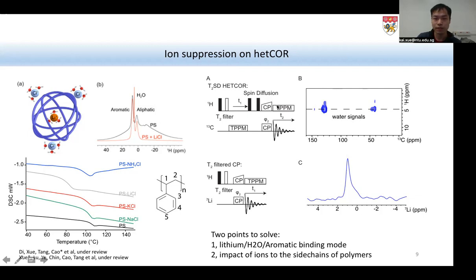And this is what we observed. Since this is a distance reachable by spin diffusion, we think the distance between protons from water and the protons from polystyrene is something like within 5 angstroms. After this proof, we also would like to prove that water is close to the ion. First of all, we also need a T2 filter to make sure that the origin of the signals is all from the water. Then we use a CP, and on the 7Li spectrum, we see a peak here.